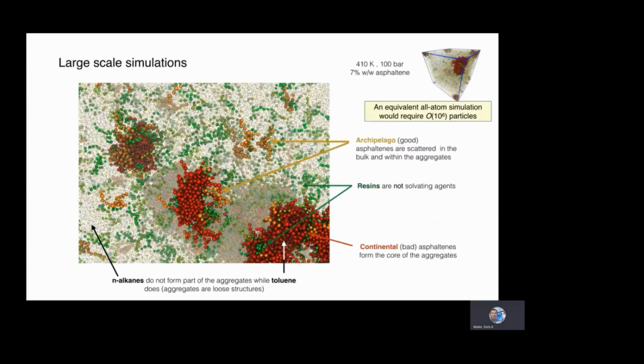We performed extremely large-scale simulations in these systems, and for some conditions, we actually saw the expected aggregation. What we saw was that for the continental ones, which we called bad asphaltenes, the red ones in this plot, there was a significant self-aggregation of these systems. While the archipelago ones, which have the same molecular weight but different conformations, would remain in suspension and would not really form part of these large clusters.